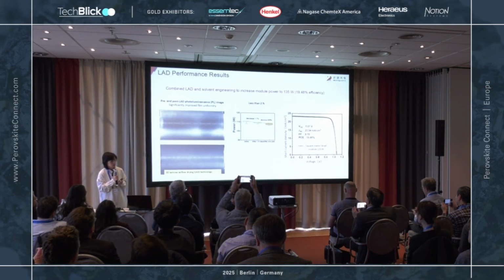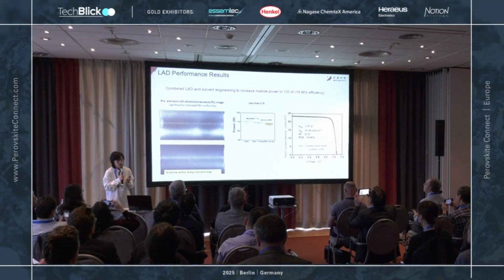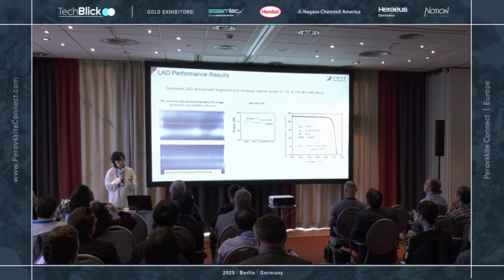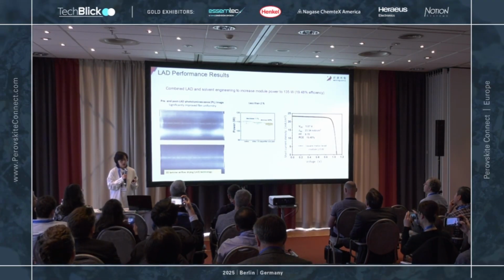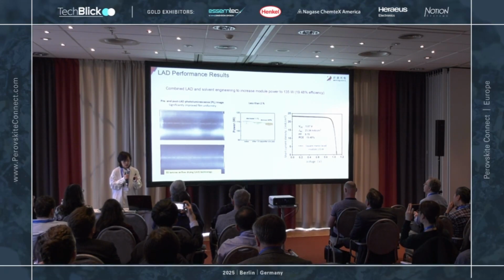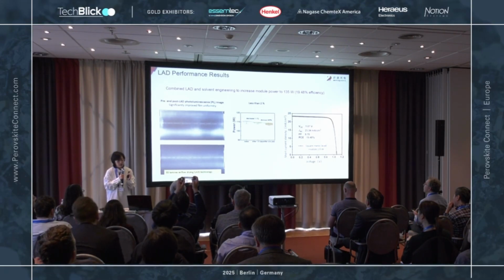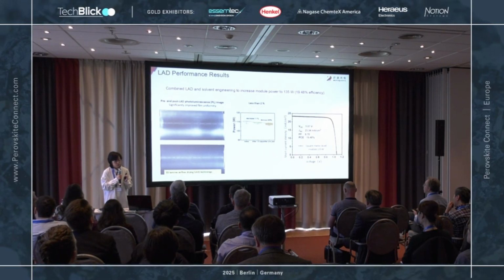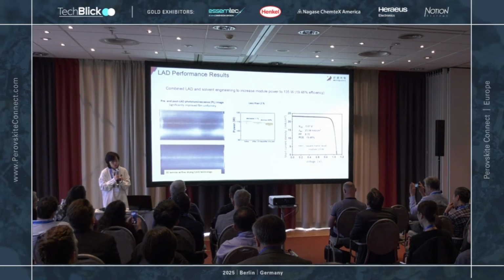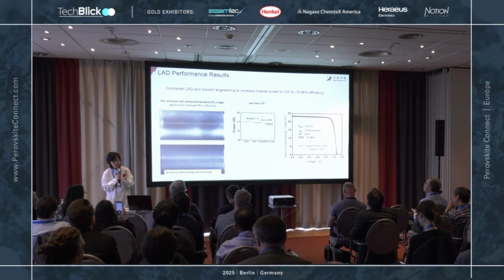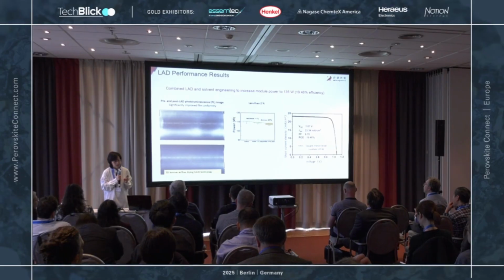Here are some results we have from this laminar dryer. In the PL image, you can see most of the dark spots are gone, and it looks perfect. In the middle, we did a 1-year outdoor test, and we found that only 2% of the efficiency is lost. And on the right side, we have a 125 watt module with 19.48% efficiency and a fill factor of 0.78.